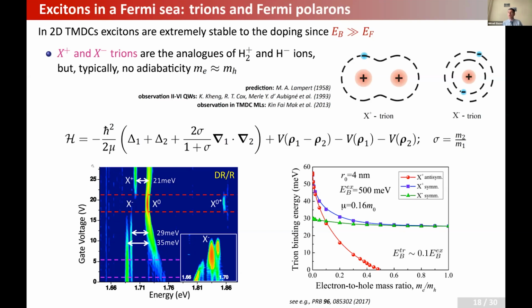You can see in this experimental plot, you have the neutral exciton. In principle, you have some excited state of exciton. But more importantly, if you add holes, you get another line below the exciton, which can be associated to the formation of a trion. So you pick up a resident electron from the Fermi sea, and you get this three-particle bound state. If you go to the n-doped case, you can see a doublet here, and again, it is the feature related to the trion, and the fact that we have a doublet here is related to the specifics of the band structure of these transition metal dichalcogenides. I will try to explain it in a minute.